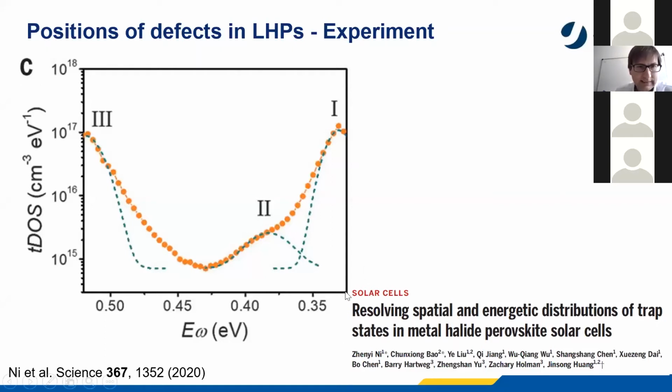And what you can see here would be a density of states, and that would be energetic position relative to either conduction or valence band edge, which you don't really know. And you can see that this is a relatively small range of energy that you can access with this method. If you're generally interested in these types of frequency and temperature dependent methods to determine trap densities, there's also a poster I've seen from Germà Garcia-Belmonte on the validity of these methods.